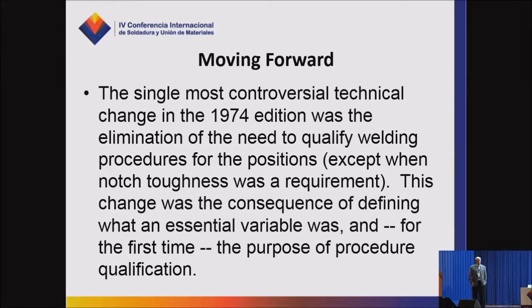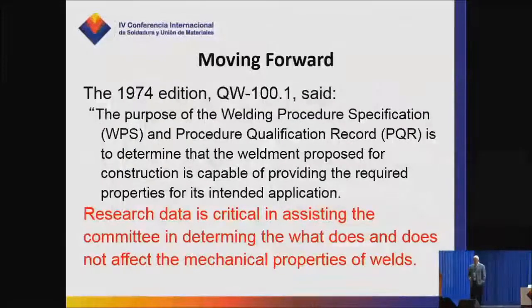The biggest and most controversial change that occurred in 1974 was the elimination of position from the requirements for procedure qualification. That is, prior to 1974, as I mentioned earlier, if you were going to weld in vertical position, your procedure had to be qualified in vertical position. That was eliminated in 1974 because, for the first time, Section 9 defined why you qualified welding procedures.